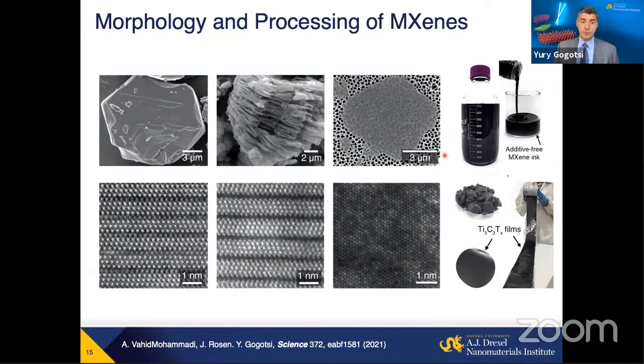We can do solution processes and still get 10, 20 micron flakes of these materials. Moreover, what is nice, you take the powder, delaminate it, and make this colloidal solution. This is a 1 liter bottle with probably a 10, 20 milligram per milliliter solution. You can concentrate it, you can make liquid crystalline solution, you can filter it into a film, or you can